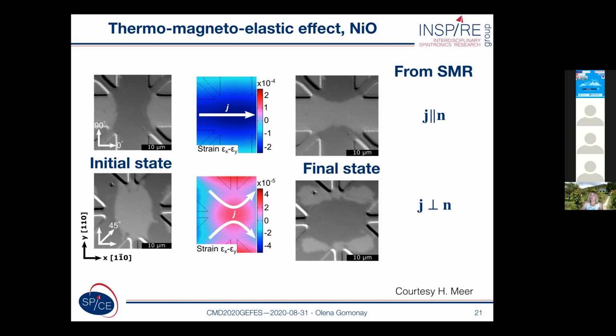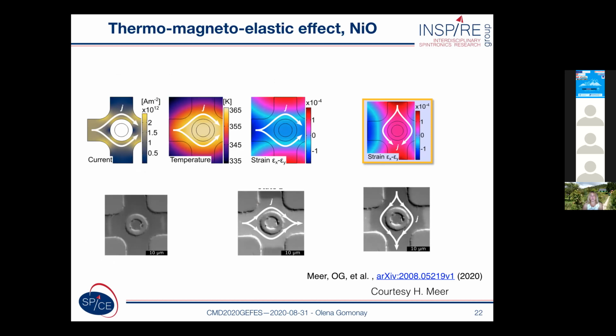To have more evidence of a thermomagnetoelastic mechanism, we tried to eliminate the direct effect of spin-orbit torques on the switching. And for this, we made a special design of the platinum electrodes, which had a hole in the center of the sample, so that the current flows only around this hole and does not produce any direct spin-orbit torques on the central region of the sample.